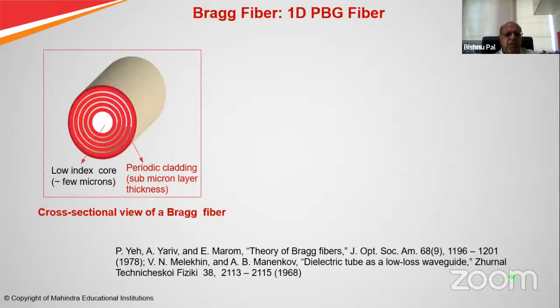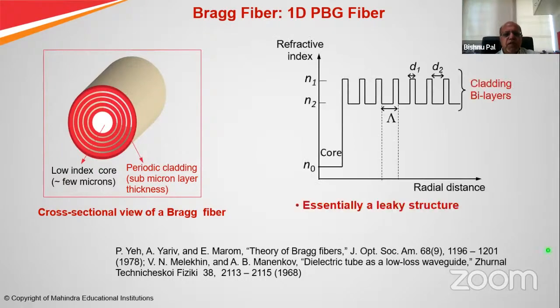So this is a Bragg fiber of the kind that we worked on, which is a low index region surrounded by concentric alternate high and low index regions. If you plot the refractive index profile, it looks like this: alternate high and low refractive index regions of certain width, with spacing lambda, and the central region is lower index than the average index of this region. So essentially, it is a leaky structure because you have a low index core surrounded by effectively higher refractive